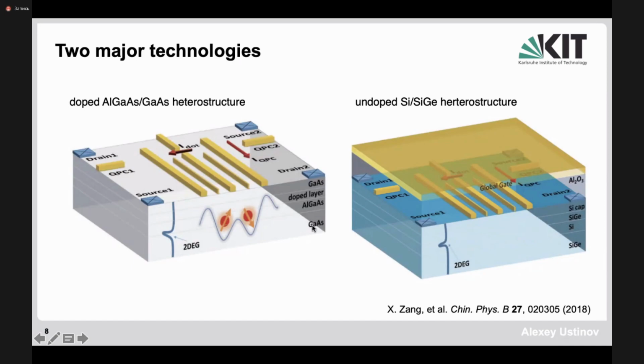And then you have some layers which are used to form a two-dimensional gas. This is the aluminum gallium arsenide and then a doped layer with a cap for the left structure. And then there is silicon germanium, and a silicon cap layer for the right structure. Now, this technology was developed a bit later. I think now they also can show very, very high mobility, but there is a tremendous advantage of silicon germanium heterostructures relative to gallium arsenide heterostructures.